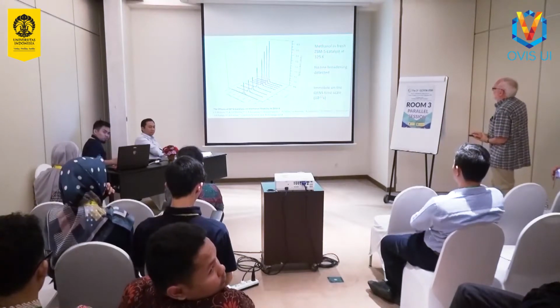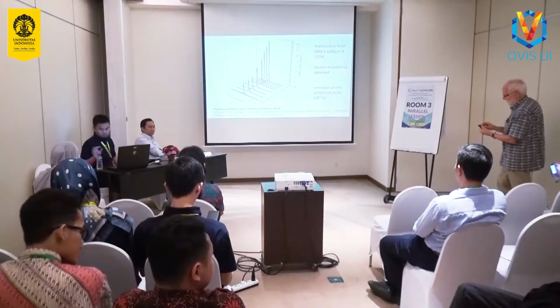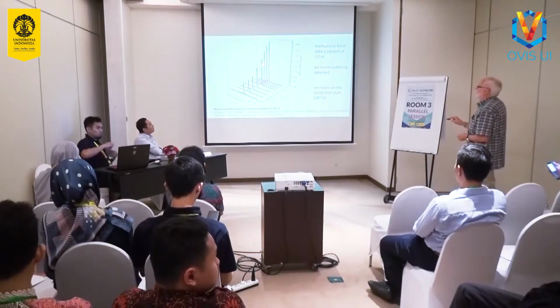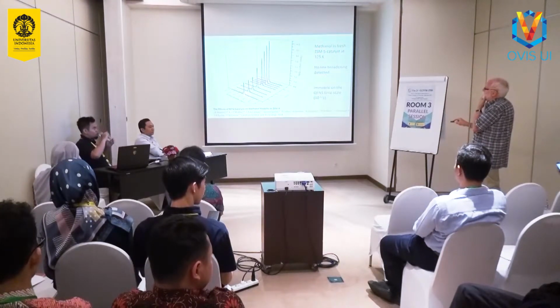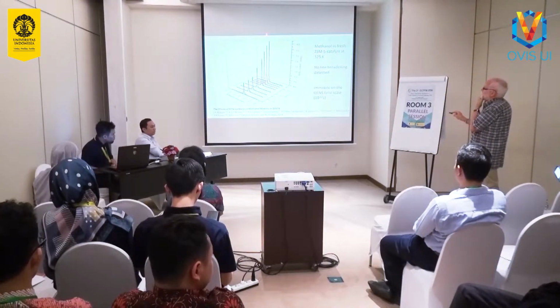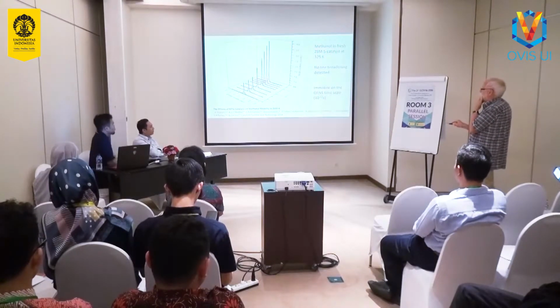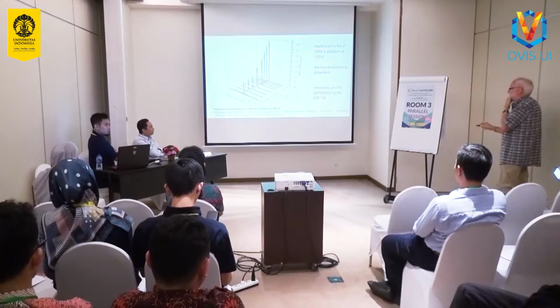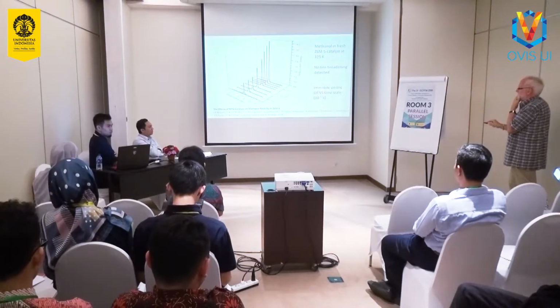However, if we put methanol into a fresh ZSM5 catalyst, 325 K, just a bit above room temperature, we see no broadening at all. This is a series of spectra at different values of Q, and all we're seeing there is this sharp resolution function. There's no broadening at all. In other words, on the time scale of the QENS experiment, down to 10 to the minus 12 seconds, the methanol is immobile.